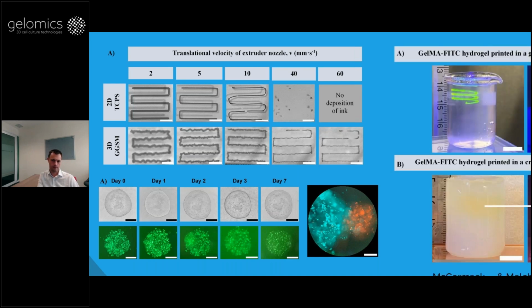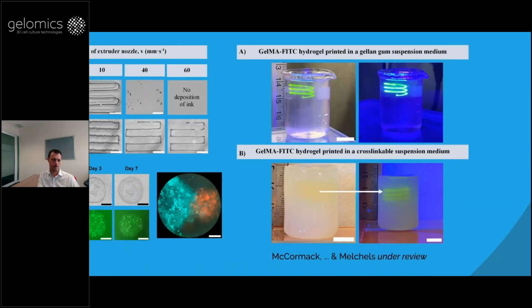So you might think, but that suspension media, that's not GelMA, that's gellan gum. True, that is how we used it first at the top here, but then we also made a photocurable one combining the gellan gum particles, the granular gel, with GelMA. So this suspension media can be cured afterwards.